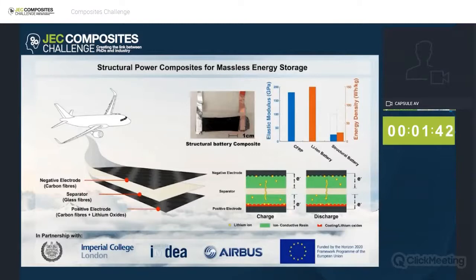As you will find on the graph, we could achieve a structural battery with an energy density of 24 watt-hours per kilogram and an elastic modulus of 25 gigapascal. By improving our manufacturing process, we could triple or quadruple these values. But neither the elastic modulus nor the energy density of the structural battery will ever equal or even exceed the elastic modulus of a conventional carbon composite or the energy density of a conventional battery pack, like the one you would find in a Tesla car.